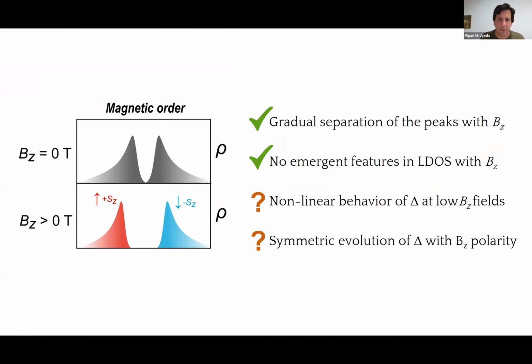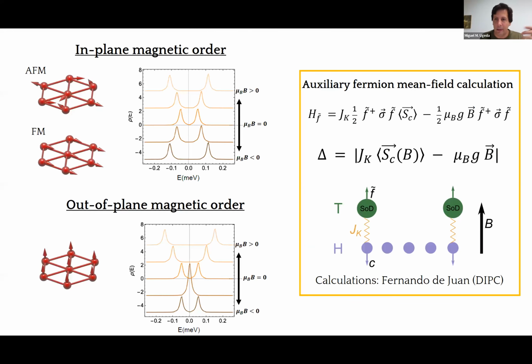Okay, so once we have gathered all this information, the gradual separation of the peaks is compatible with the magnetic order. The fact that we see no emergent features in the density of states is also compatible with the magnetic order. So the question that is still open is whether this nonlinear behavior and the symmetric evolution of the separation of the peaks is also compatible with the magnetic order. So at this stage, we carried out a minimal model using a mean field calculation that was carried out by Fernando de Juan here, who is an excellent theorist here at the DIPC.